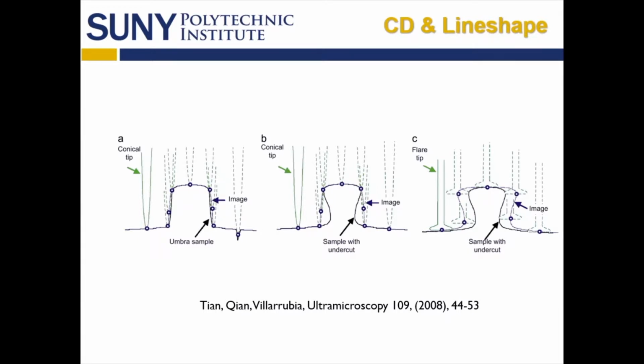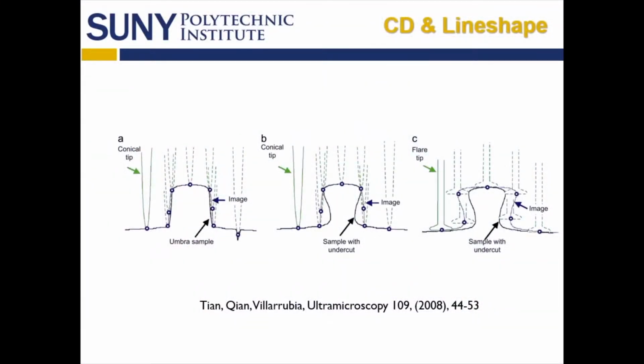Now looking a little bit more recently, CD measurements and surface shape measurement, 2D shape measurements, 3D shape measurements, sidewall roughness, and along the length of the line roughness are all important quantities. And so a particularly useful name if you're going to go Google searching on Google Scholar is John Villarubia at NIST, and here's one of his papers. And so what we're showing here is that if you have a typical shape for your AFM tip and you had a sample undercut, you might not see that undercut.